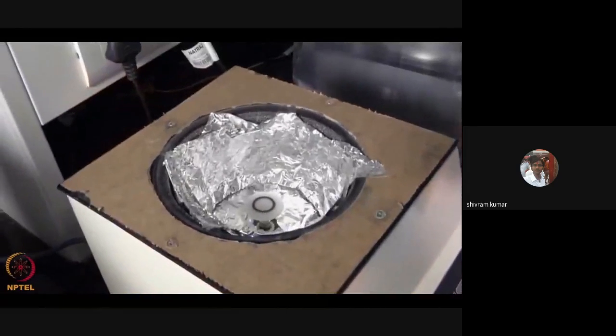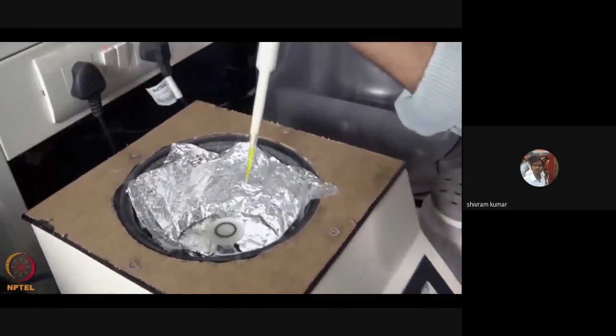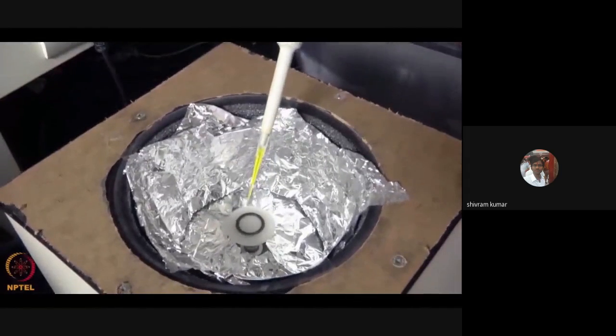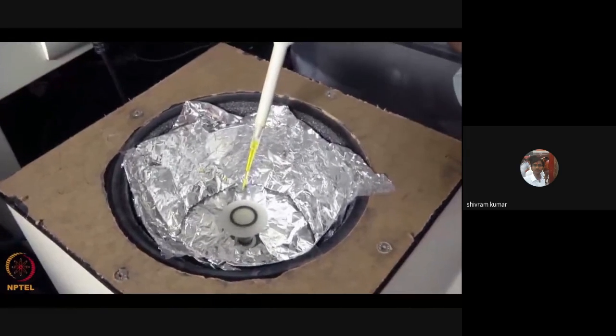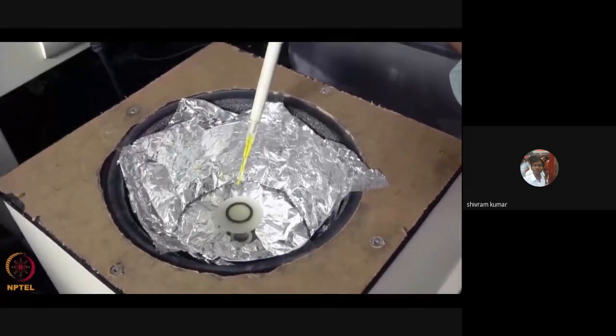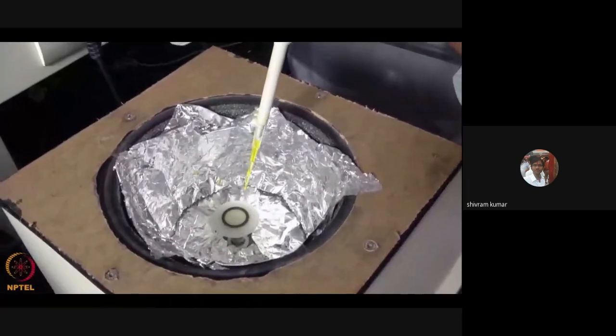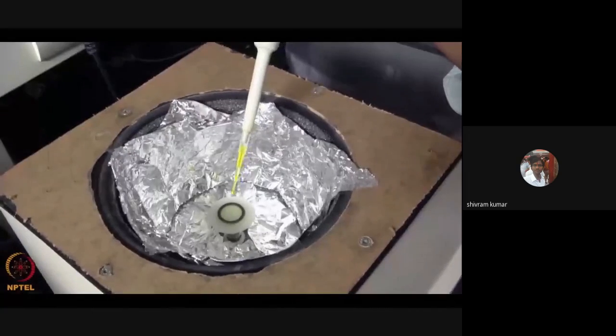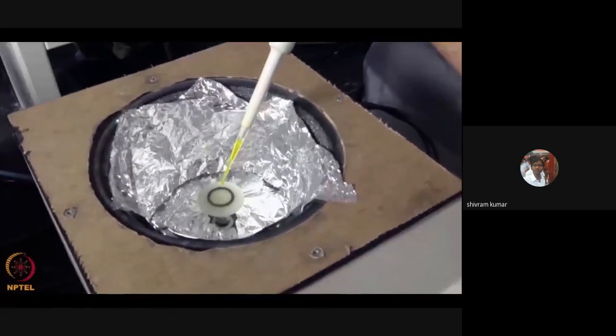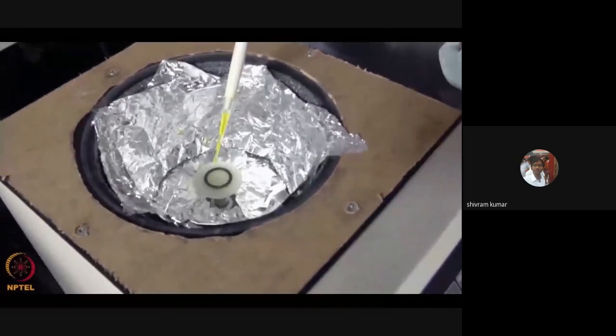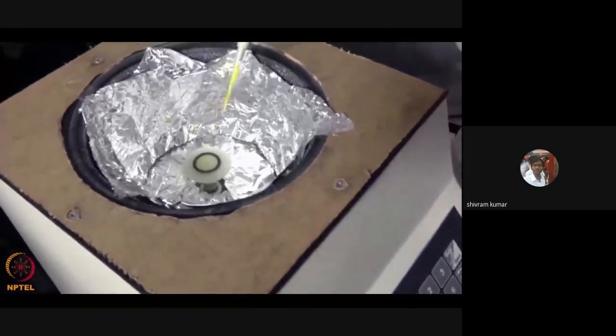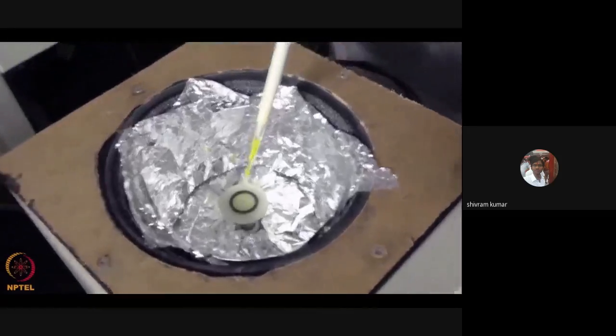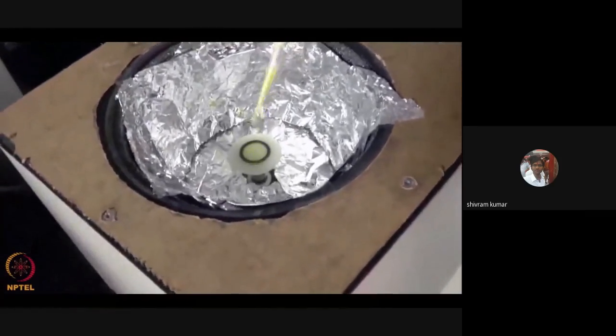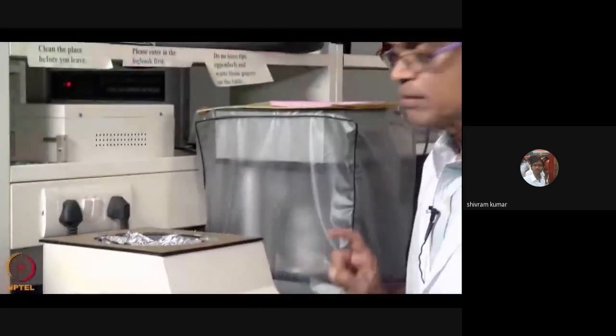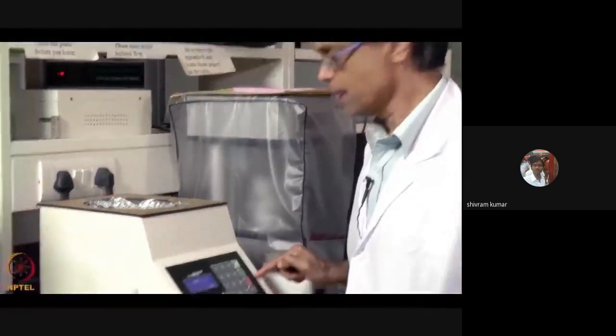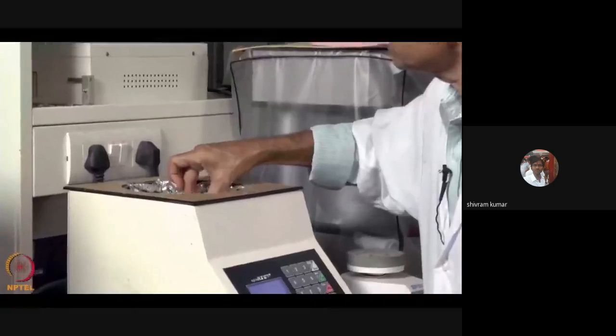I take this solution and add slowly, drop by drop. And as you can see, it gets uniformly distributed along the polymer surface. It forms a monolayer. Once the coating has been done, we switch off the program, stop the program, we can remove the glass slide.